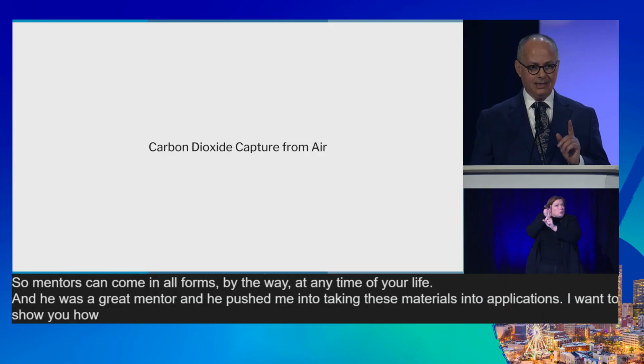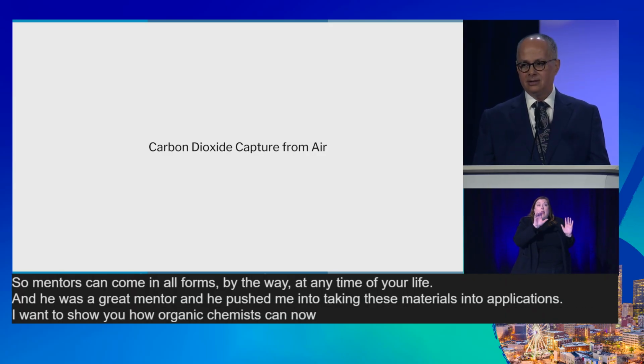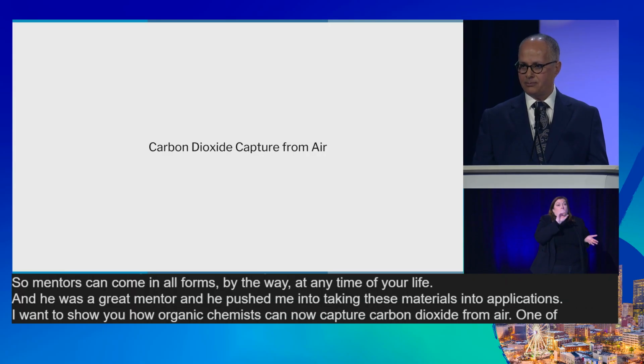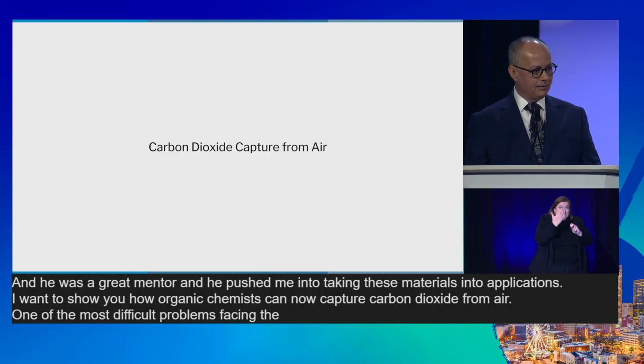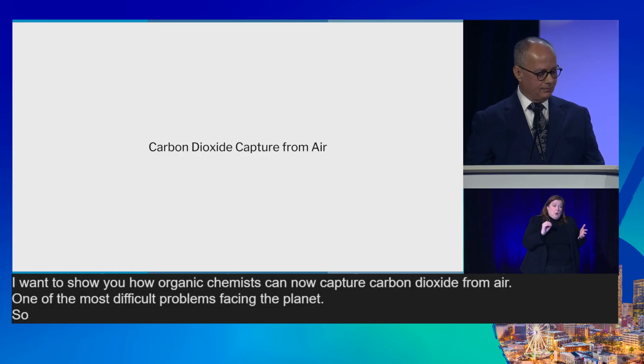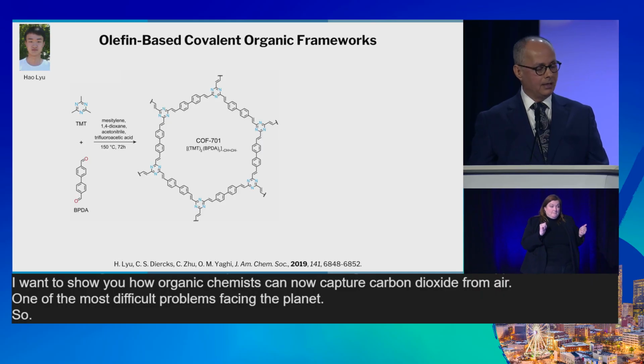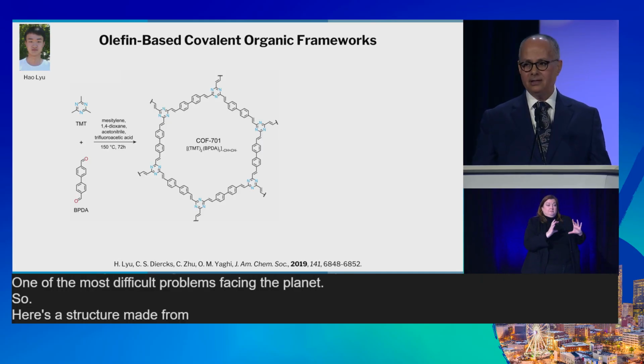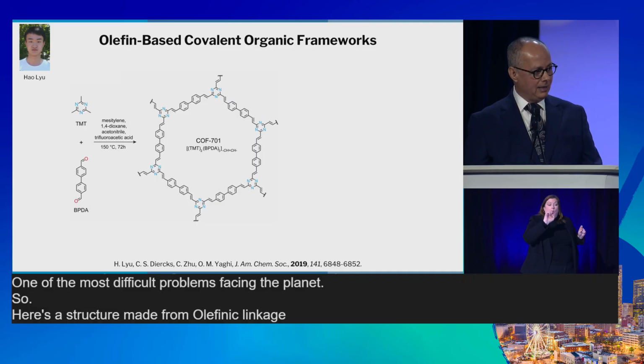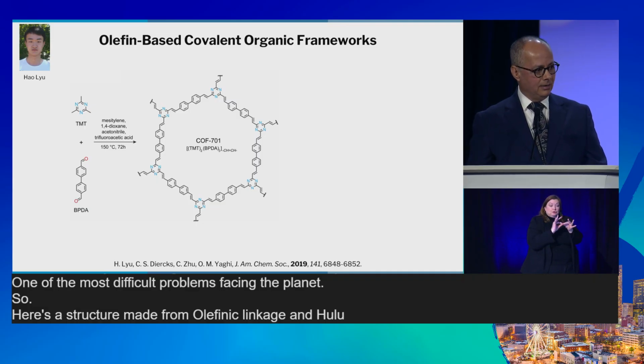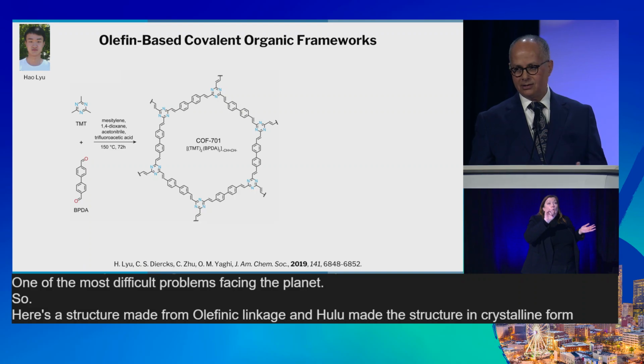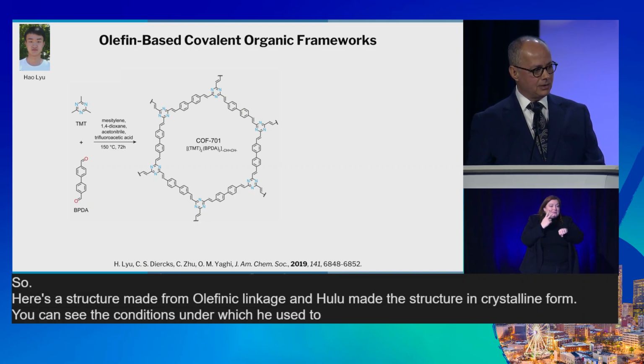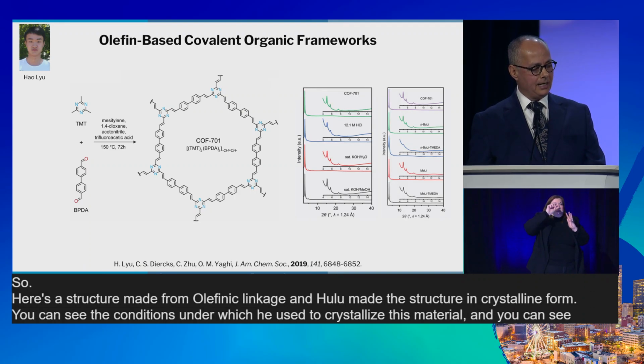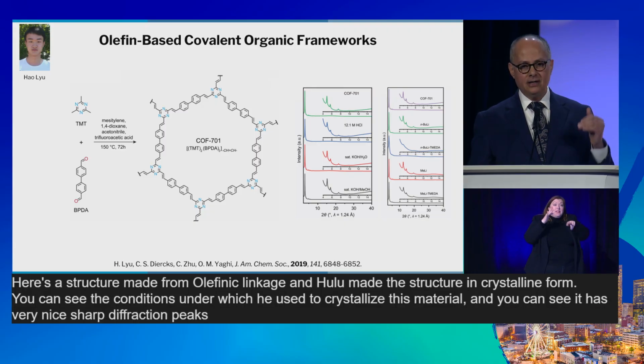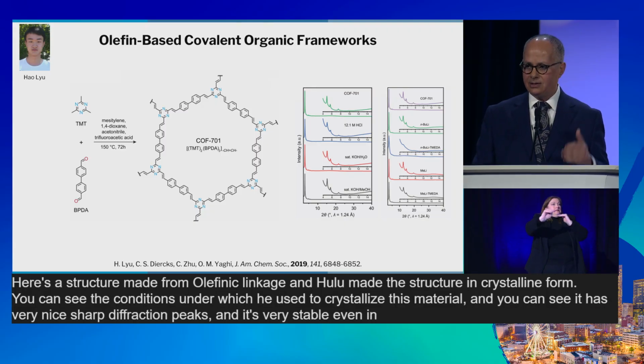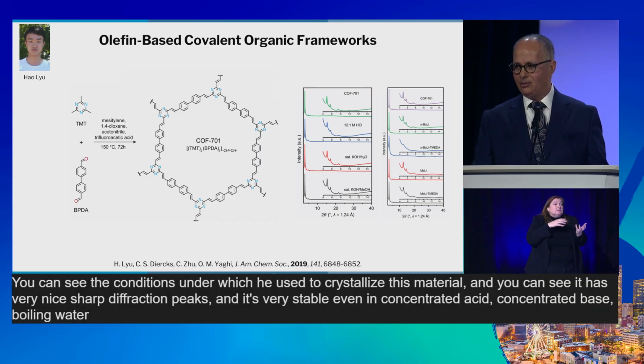I want to show you how organic chemists can now capture carbon dioxide from air, one of the most difficult problems facing the planet. So here's a structure made from olefinic linkage. And Hao Lyu made the structure in crystalline form. You can see the conditions under which he crystallized this material, and you can see it has very nice sharp diffraction peaks, and it's very stable even in concentrated acid, concentrated base, boiling water, anything you want.